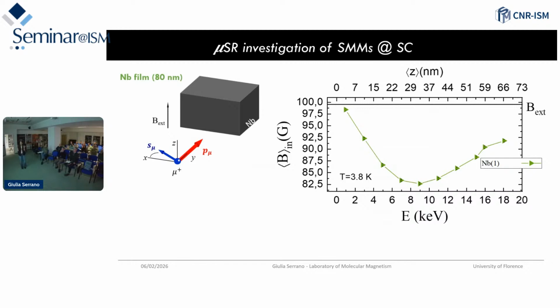So what we have done is to use a niobium film to probe this decay by spectroscopy that we have within the superconductor, and to understand how this decay is changed or altered when we put molecules on top.